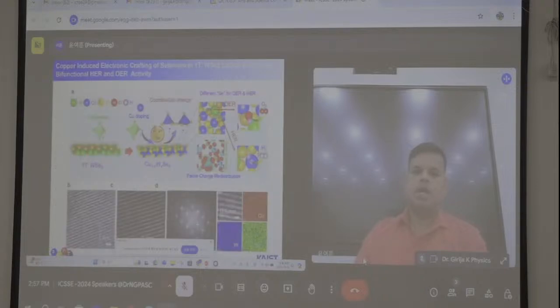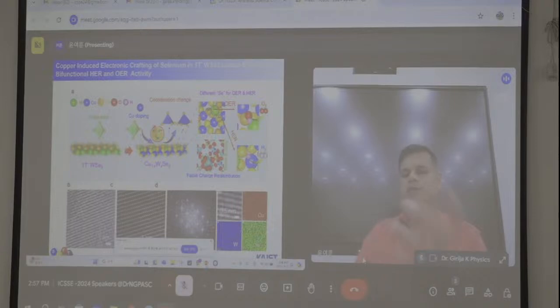Yes. So in another study we also developed materials, and we also analyzed that material. You can see copper with different doping behavior. But when copper is doped into the tungsten selenide substrate, what changes happen? How is the selenium changed? There are different types of selenium, maybe one with a plus charge and another with a minus charge. Maybe one side acts as an OER site and another one as an HER site. And we also studied that the 1T prime phase is maintained even when doping a higher amount of copper. We also did imaging at the 0.5 nanometer scale bar. You can see the homogeneous distribution.